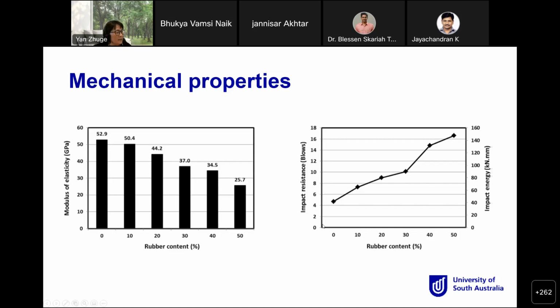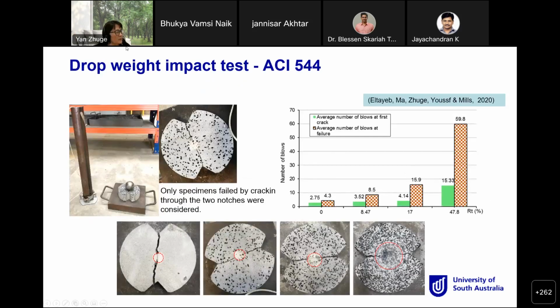Okay. Another advantage of crumb rubber concrete is the impact resistance. This is also well known. You can see if you increase the content of rubber, there is a big sharp increase of the impact resistance. So that's another advantage: crumb rubber concrete could be used as a protective structure. If you have protective structures against impact loading like bombing or something, there are advantages there for crumb rubber. So the next slide shows you some more details about drop weight impact testing.